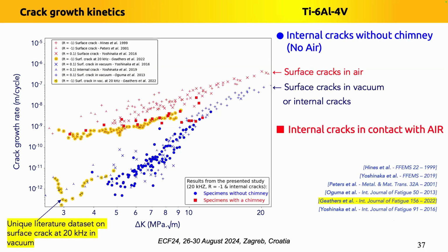It is interesting to compare our results to a surface crack in vacuum at the same loading frequency as our experiments, that is 20 kilohertz. According to our knowledge, there is a unique study published by Geathers and co-workers from Michigan University, and I reported their data here. This experiment corresponds to, again, a titanium alloy, similar to our titanium, but with a surface crack in vacuum. And you can see that in this case, the surface crack, this is a point surrounded in yellow here, propagates similarly to our internal cracks.